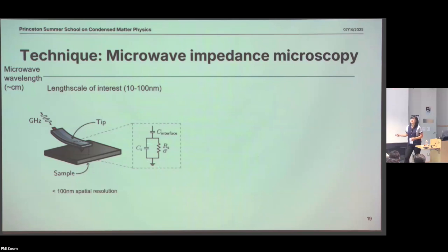Then we measure the reflected microwave coming out of the tip. It's slightly different from the far-field or global microwave measurement, in that here the sample is only inducing a perturbation of the signal. It's not the full signal that you measure from the reflectance. So if we define the reflectivity as gamma, then gamma is around gamma-naught, which is the case when you don't have the sample underneath, and then you put on this small perturbation, dΓ/dY, where Ys is the sample admittance. With that small perturbation, we can directly get this information out.